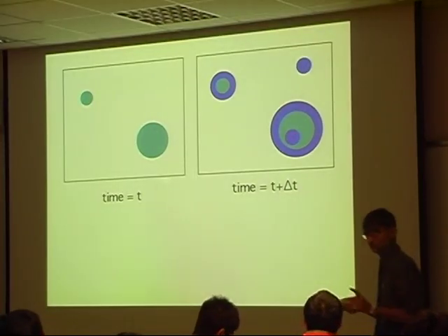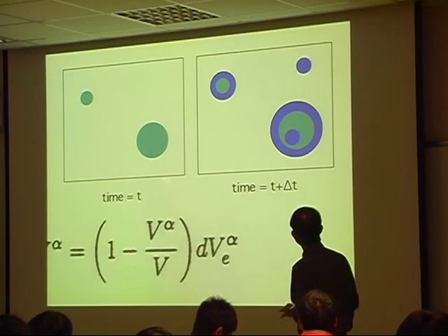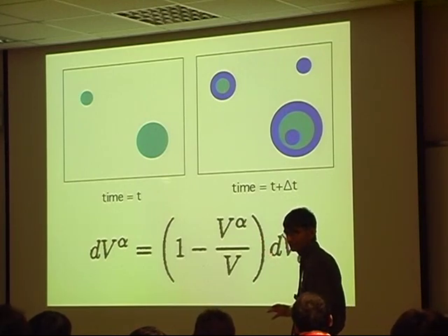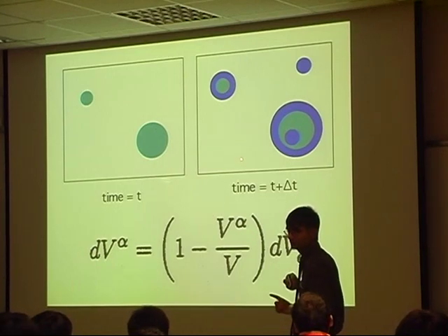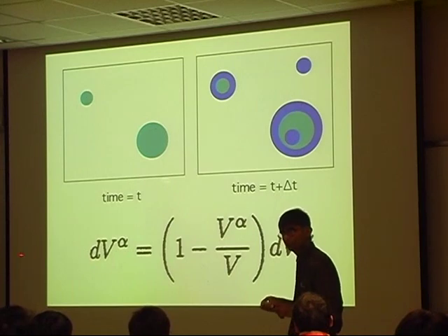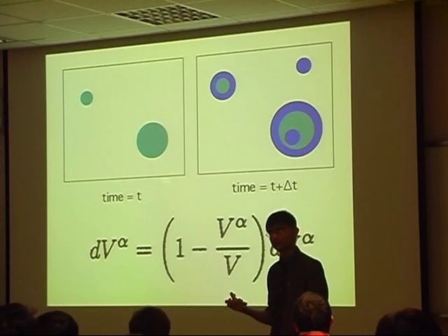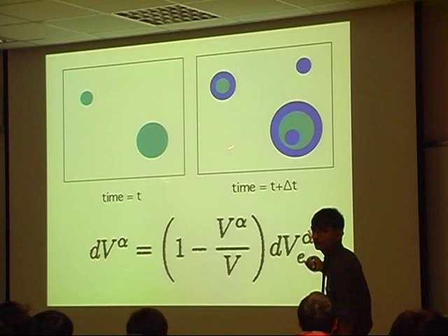This particle obviously is wrong. Okay. And Avrami already has corrected for that, because if I add up all these dark blue areas, I get the wrong change in volume fraction. But if I multiply that by the probability of finding untransformed austenite, then I get the true change in volume fraction. So this is the major achievement of Avrami, that he multiplies by the probability of finding untransformed material. And it's very, very clever, I think. Once you do that, you correct for errors like this, or even when two particles are growing into each other.